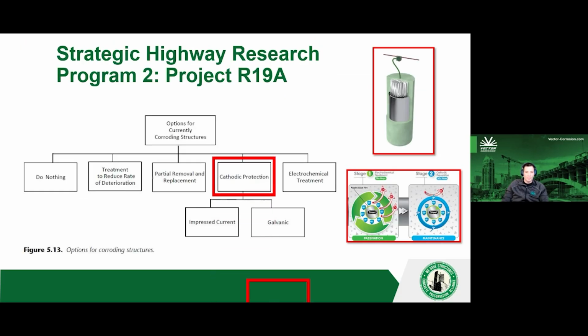So they looked at this other option, which uses a fusion two-stage anode, where it has an impressed current piece. In this case, it's a fancy way of saying a battery, where a higher current is pushed out initially to passivate this currently corroding steel. And then once that higher current is depleted, the battery is depleted, it will naturally switch over to this galvanic piece, the zinc, and the maintenance requirements of current are much, much lower for something that has been passivated. The analogy here you can think of is friction, static friction versus kinetic friction. It's harder to get something moving than it is to keep it moving. So once you have it moving, it's easier to keep it there. Once you have something passive, it's easier to keep it there.